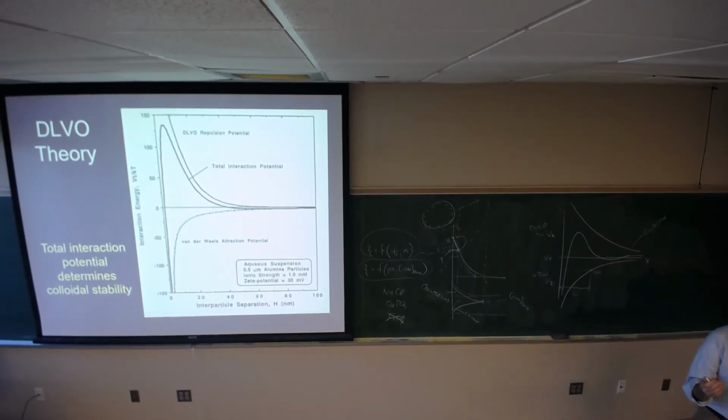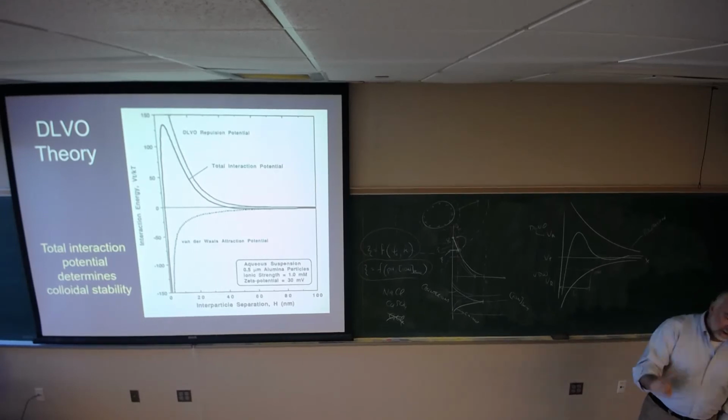So let's say I give you a suspension of particles and you wish to disperse that suspension. What do you do? Change the pH. How do you change the pH? Away from the point of zero charge. Keep that in mind, please. It's a rather amorphous idea, right? We really like this idea of the isoelectric point. We go, oh, I'll go to the isoelectric point, which is the perfect pH to flocculate my suspensions, right? But we can define it, so we like it. Say I have to move it away, the question is how far.